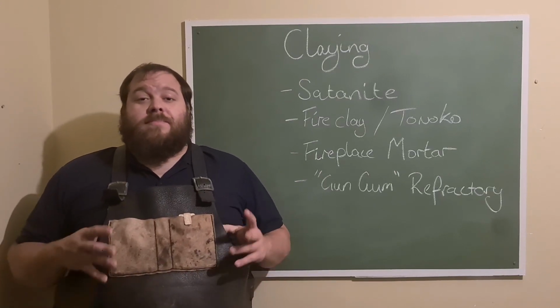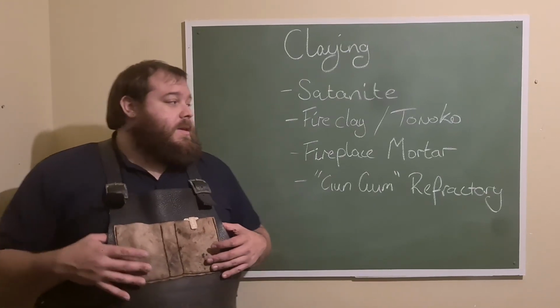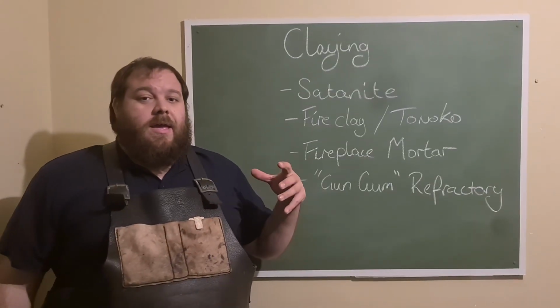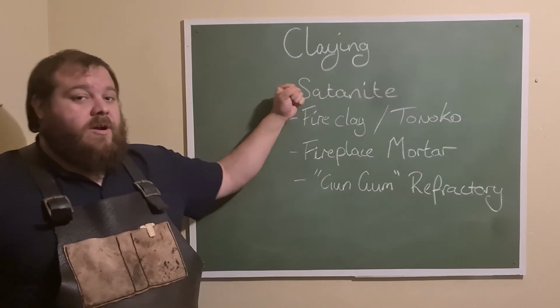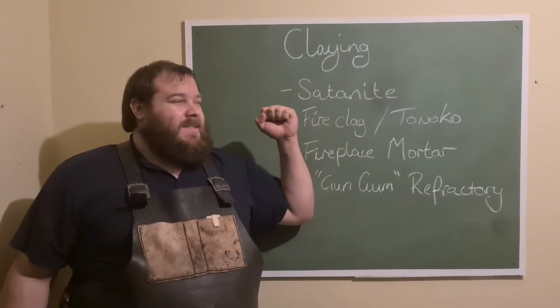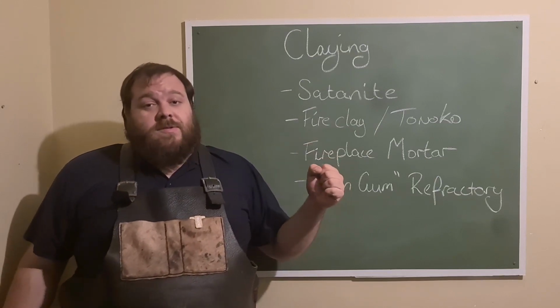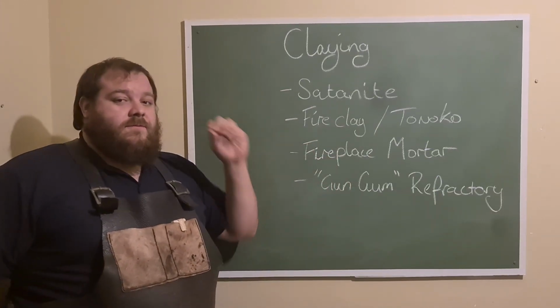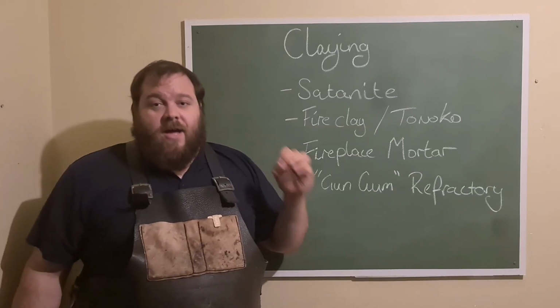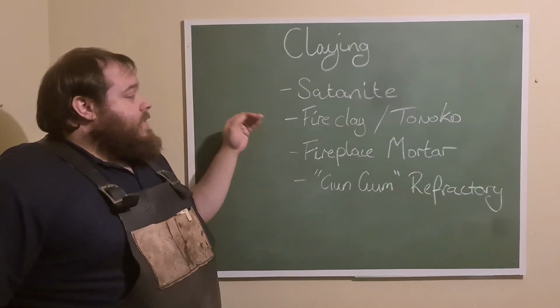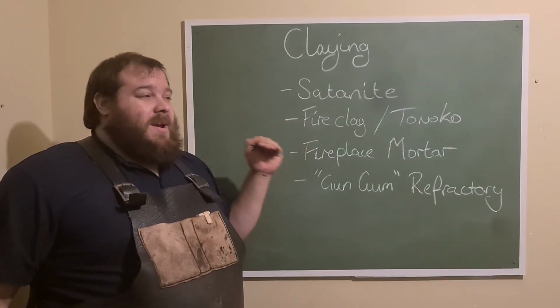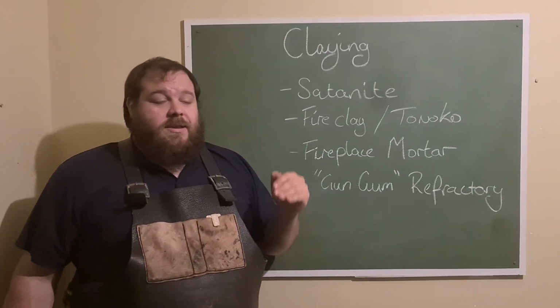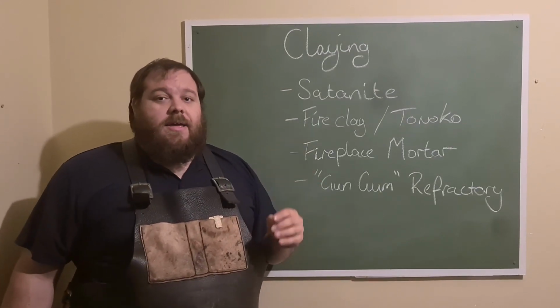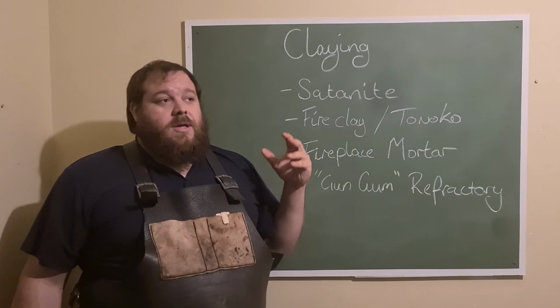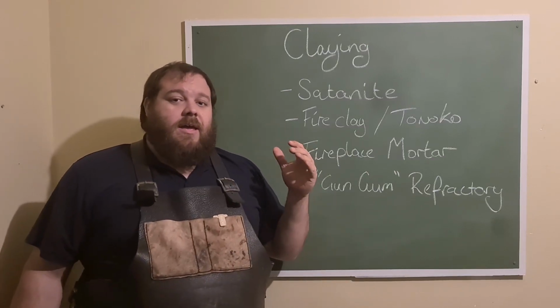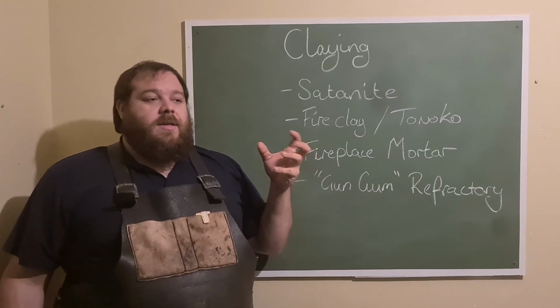Another thing to be mindful of when making Hamon is what clay to use. Now, in the West, we mostly use a version of Satanite, which is a very high temperature refractory wash. It's not really a refractory cement, but it can be used as such. But it is a very thin, very fine powder clay that is designed for high temperature use. In Japan, they use tonoko, which is a form of fire clay, but it is basically a version of terracotta. It is a very simple ground clay that is basically a fine mesh. So it is possible to use a clay like pottery clay, as long as it's not been fired, obviously.